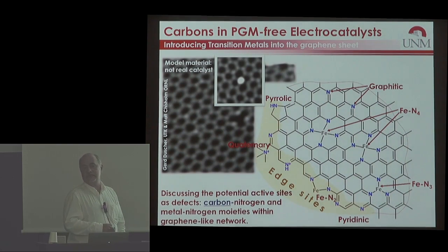I'm here to understand where this iron goes. And iron can go into essentially three different places. Either in a double vacancy, and then you will see later with DFT calculation, it can sink entirely in plane and stay there in both valences, 2 and 3. Or it can go in a single vacancy surrounded by nitrogen, and then it has to stick out of plane because there is no room for it to sink in the plane fully. It will stick about 1.2 angstrom above the plane. Or it can go and coordinate on the edge defect with an unfilled coordination number, and then one can fantasize how that unfilled coordination number is fully fulfilled down the road.